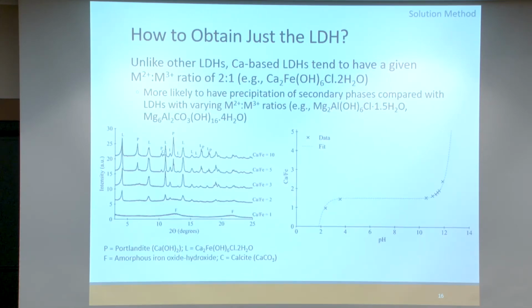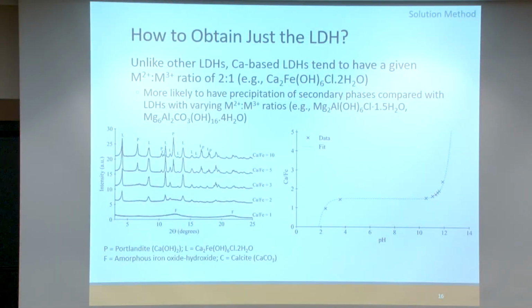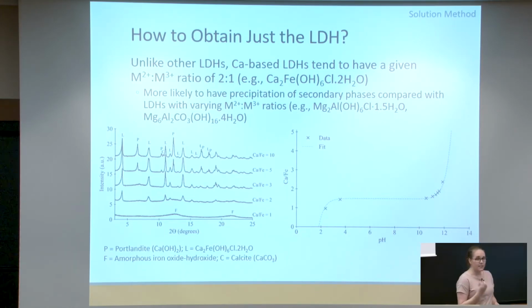The other thing to keep in mind is that these layered double hydroxides with calcium in them are not very forgiving if you have different ratios of these 2+ to 3+ cations. The solid always wants to have a ratio of 2 to 1, 2 calciums to 1 3+ ion. And so when you're trying to synthesize the solid, you have to be very careful with exactly how much you add of each of these solutions, because if you've got too little or too much, you're going to have these secondary phases that form. This is not the case for other layered double hydroxides, such as the magnesium-based ones, which are very easy to obtain with different ratios for the cations that are present.